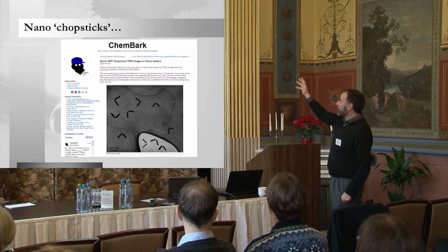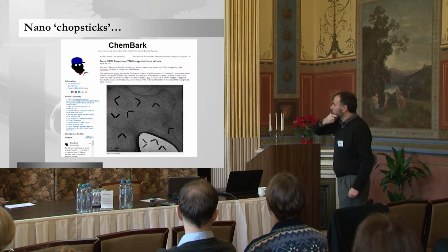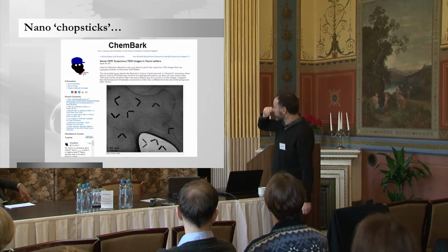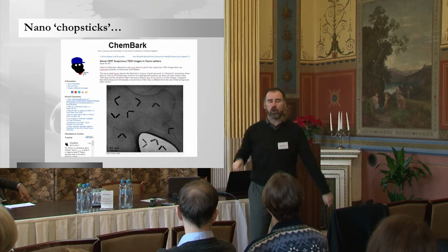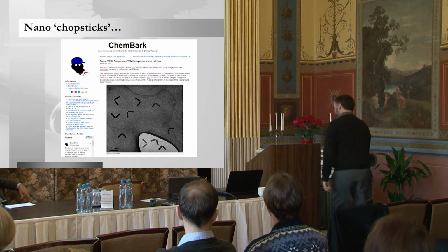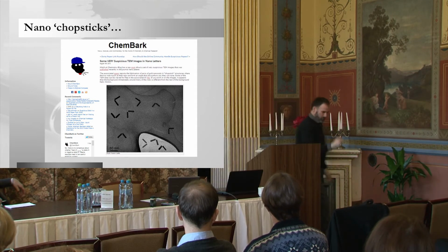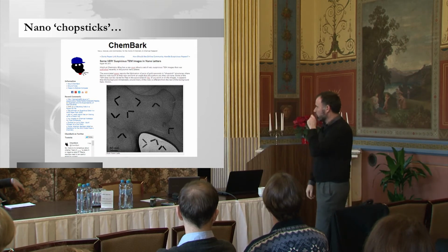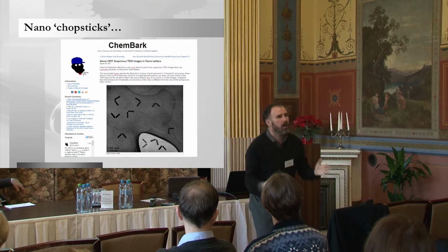And this really struck a nerve with me, because we've done a lot of work on nanoparticles and how they organize on surfaces. What this experiment is doing is pretty easy to explain. You take gold nanorods. Each one of those little things is a gold nanorod, about 50 nanometers in length, very, very small, and as you can see, about 10 nanometers or so across. You have them dissolved in a solution, and you put that solution on a surface, and you let it dry.